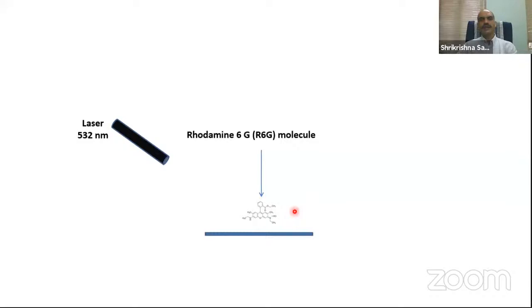I will show you what we do in our case. For example, we use the rhodamine 6G molecule, which is a very toxic pollutant that many of you know. We want to detect this rhodamine 6G molecule in water. In the beginning, I will put this molecule on the surface of, let's say, glass, and then I will incident the laser. There will be Raman scattering, and I will detect this scattering with the detector, or the Raman spectrometer.